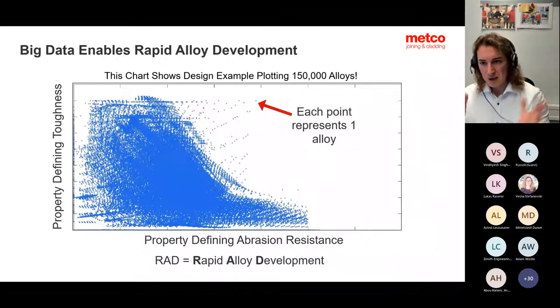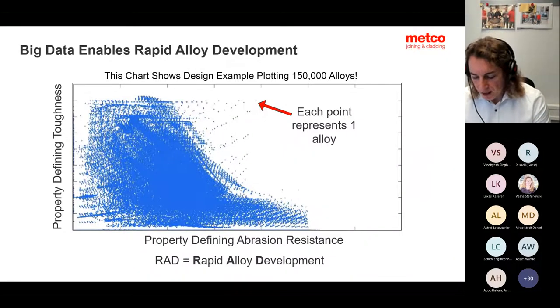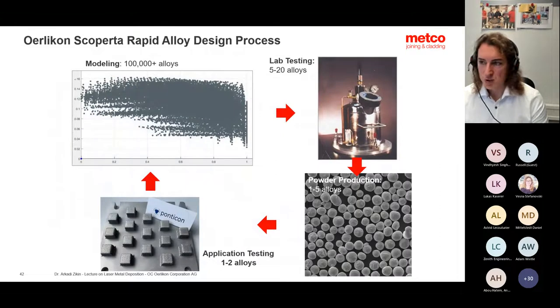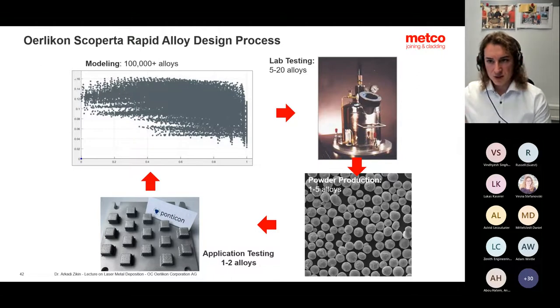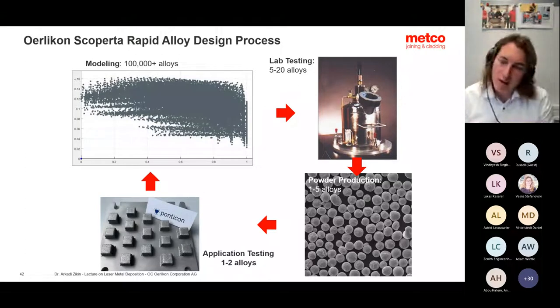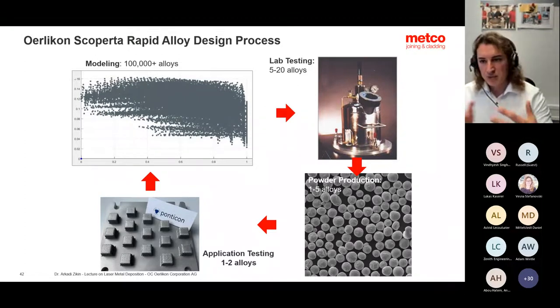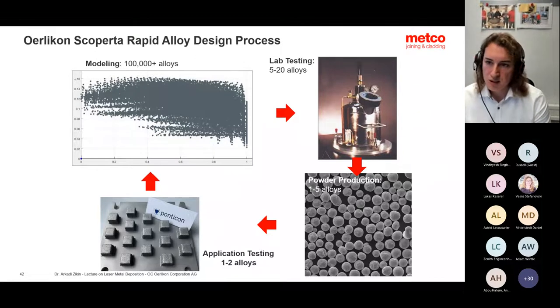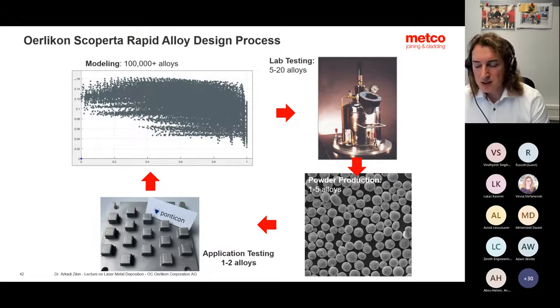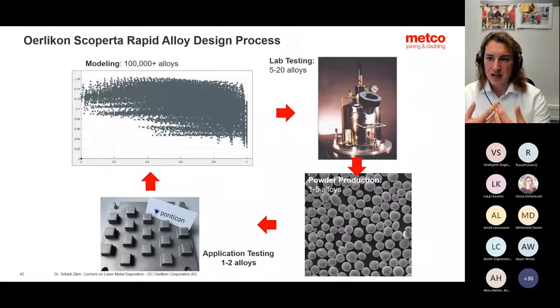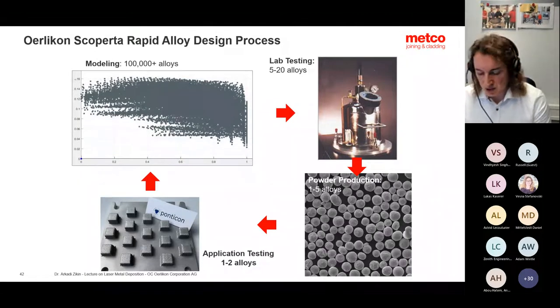So with down selecting possibilities of rapid alloy development, you just select from this chart like 20 chemistries which can correspond to requirements you need, and then based on this you can produce only like 1 to 5 powders which go to rapid testing using, for example, new technologies in terms of high speed, which really gives you a chance of fast testing of material properties and understanding if this type of chemistry might be turned to a product.